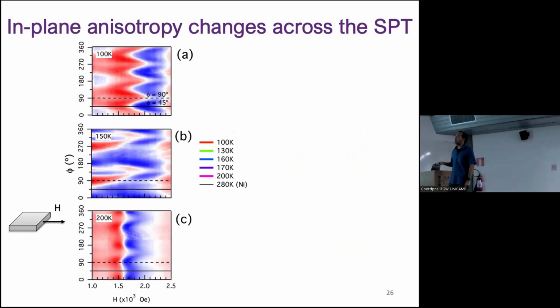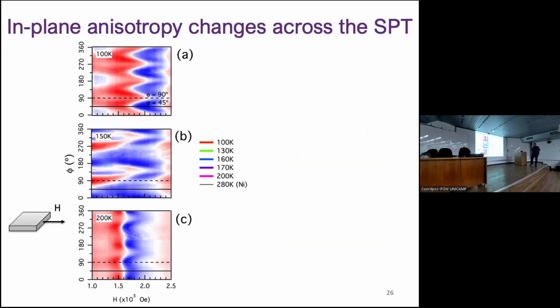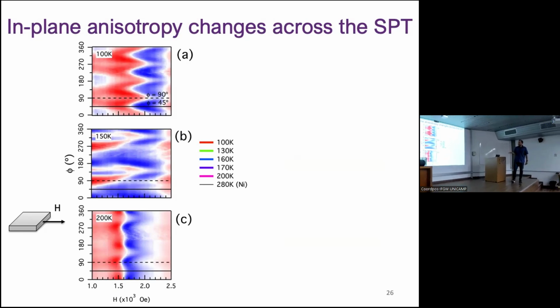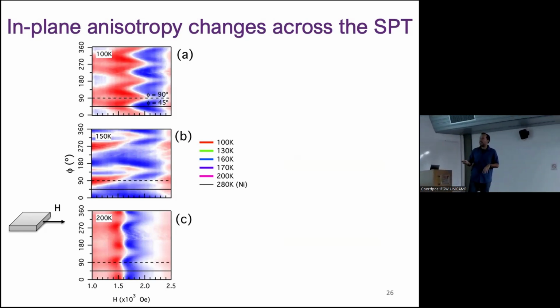Then we did some in-plane studies. So I now apply the magnetic field in the plane, and if I apply it in the plane, I see different stuff. I see how the crystal structure, basically the symmetries of that, appear when the phase transition occurs, right? So I see all the crystallographic things. For instance, at low temperature you see that this is exactly 4-fold, but at high temperature it's kind of 6-fold. So you have something that is 6-fold and 4-fold.